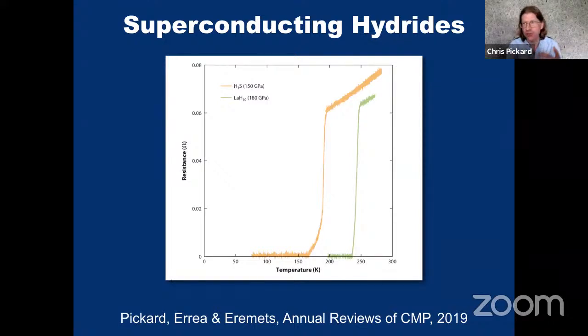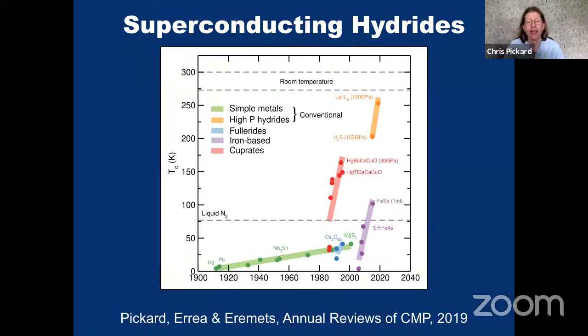superconductivity, especially with the strong prior that this is what you would expect. You'd have to work hard to explain why it's not superconducting, because when you take these structures and compute their properties, it says it's a superconductor. But time will tell. I think we need more independent groups to be able to do these experiments, and that drives a lot of our current work in trying to find superconductors that superconduct at lower pressures, because the lower the pressures we can find this superconductivity, the more experimental groups can do measurements and take more measurements.